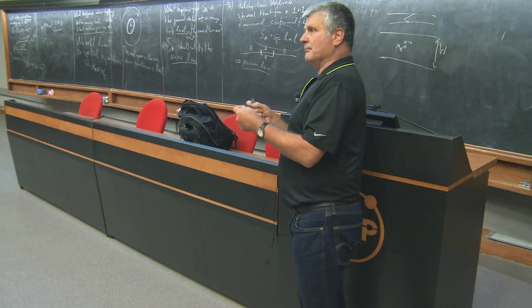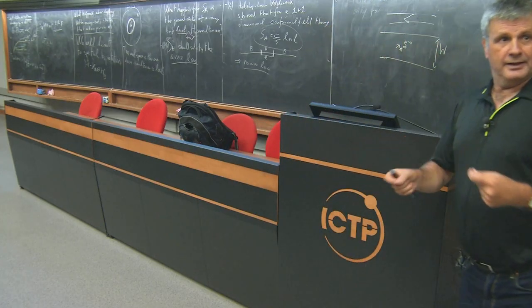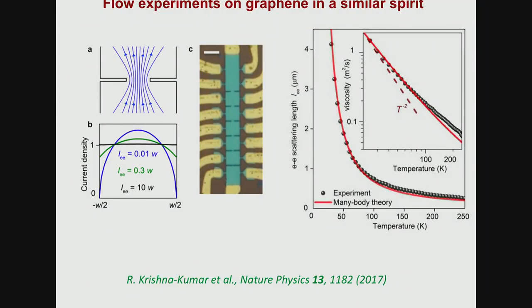So this is a very important self-consistency check. You're doing these comparisons with theory, but you then end up fitting out a parameter, and that parameter should self-consistently check whether the assumptions that you put into the theory look reasonable. And getting that T squared, I think, is a really important point. And the specialists may want to quibble with some other parts of the analysis of this experiment, but I think that point alone tells you that this result must be correct.